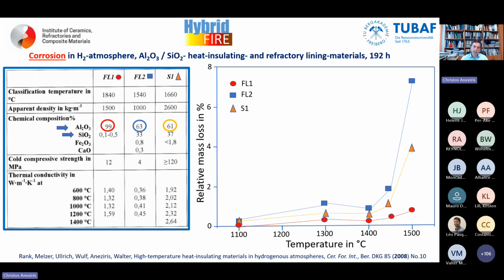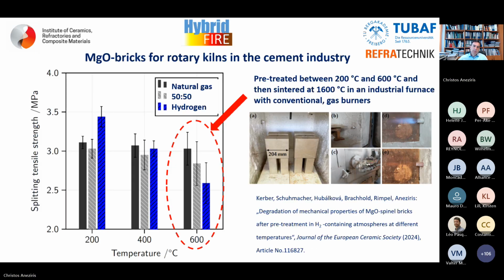So we have a high relative mass loss at temperatures above 1400 degrees, much higher in comparison to the classical pure alumina, the red one, the red circle, which is a pure alumina system. But this is not only the case in the silicate area, this is also the case in magnesia. And magnesia bricks are the lining materials for rotary kilns. And we see in the middle such kind of bricks.